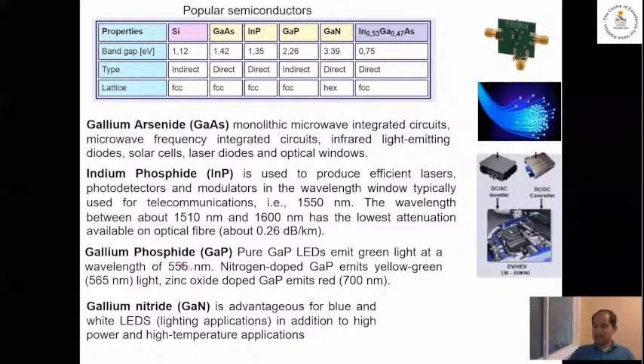And then there's also gallium phosphide with a band gap of 2.26 electron volts. This material is interesting because it can be used to build green LEDs. As you may know, the human eye is most sensitive to green light. And so green is an important part of the spectrum, and gallium phosphide helps to build devices in that range.